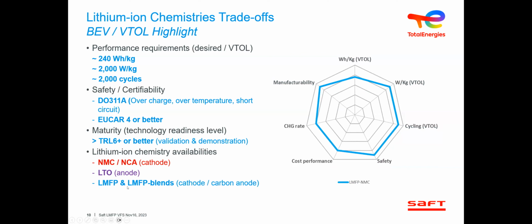The lithium manganese iron phosphate (LMFP), this is where we're going to focus today, is a cathode technology. The anode is a carbon type anode with liquid electrolyte. So all these three technologies are liquid electrolyte. It is a good compromise of specific energy. So very similar operational voltage as NMC and NCA, because it's a blend of lithium manganese phosphate and NMC. So you recover specific energy very similar to the NMC. Very good power capability as well.